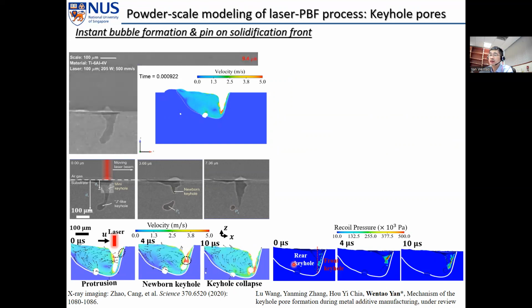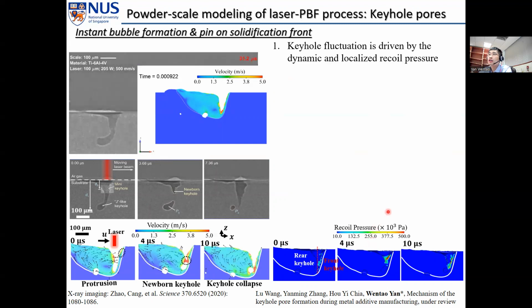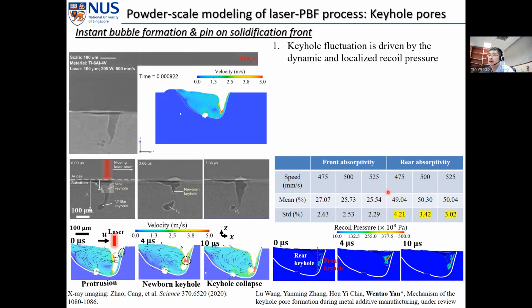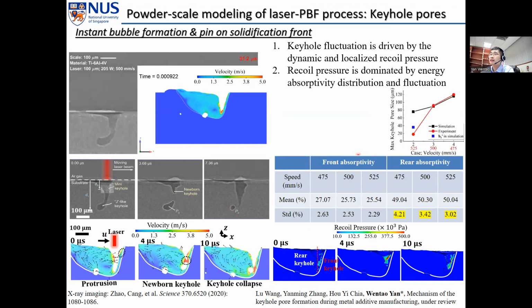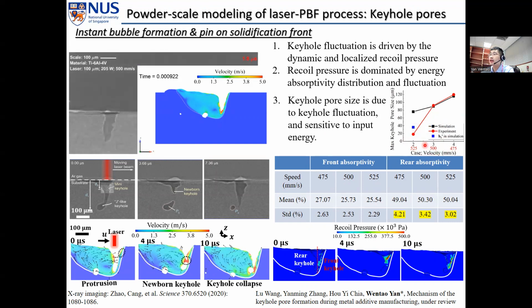Besides this, we can further reveal the driving force, which is actually the recoil pressure. Furthermore, this recoil pressure is driven by the energy. You can see the rear keyhole wall will absorb more energy, but the fluctuation is also larger. So it leads to a larger fluctuation of the rear keyhole wall, which leads to keyhole pore formation. And the keyhole pore size also agrees well between our simulation and experiments. You can see this is around the threshold value for keyhole pore formation, and it's very sensitive to the input energy in this area.